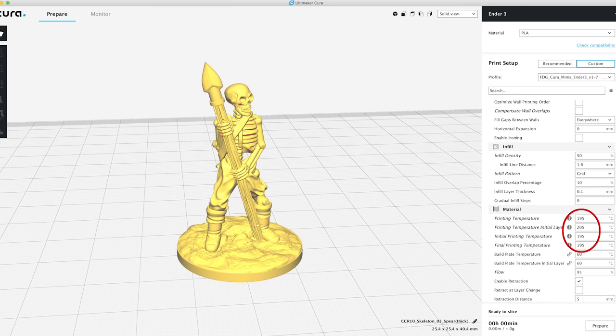If you were printing, say, at 205, you would notice more drooping on overhangs, small details would not be as sharp. So again, 195 may not work for you. You may have to print, depending on what you're using, at 200, maybe even 205, although I really can't imagine any PLAs requiring that for a miniature. But start with 195. Anytime you adjust temperatures in a case like this, never go in increments more than 5 degrees at a time. It's amazing what a difference can happen with PLA in just 5 degrees. So if you start at 195 and you're seeing under extrusion, you're going to have to go to 200. If you're printing at 195 with Hatchbox and you're seeing more issues with overhangs, you can go down to 190 and maybe even 185, but try 190 first.